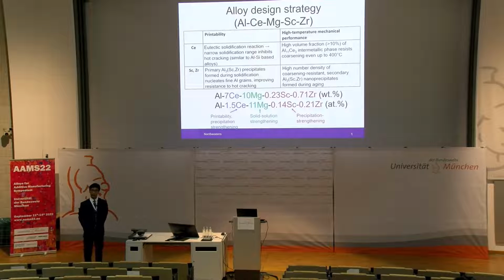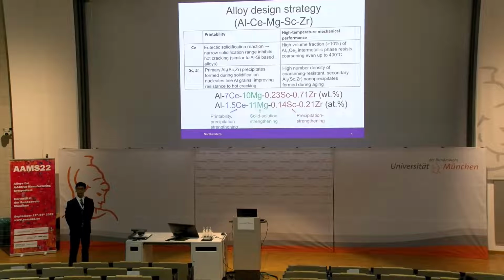So the alloy that we're working with today is this aluminum-cerium-magnesium-scandium-zirconium alloy. And we designed this alloy for two reasons. One is, of course, printability, and the second is for high temperature mechanical performance, as we want to design lightweight aluminum alloys that can replace heavier or more expensive titanium or iron-based alloys at temperatures up to about 400 degrees Celsius. Now, cerium is an element that has attracted some attention within aluminum alloys pretty recently.